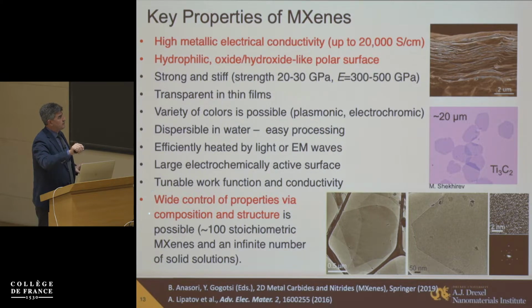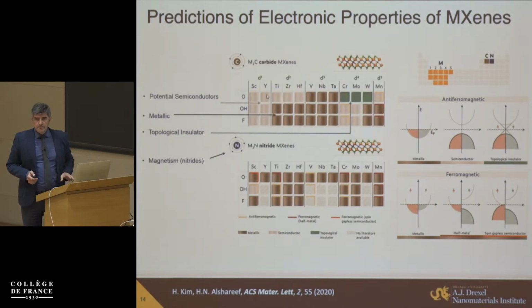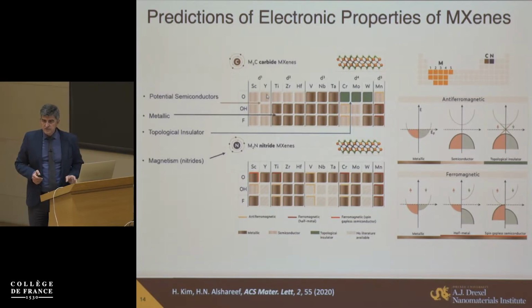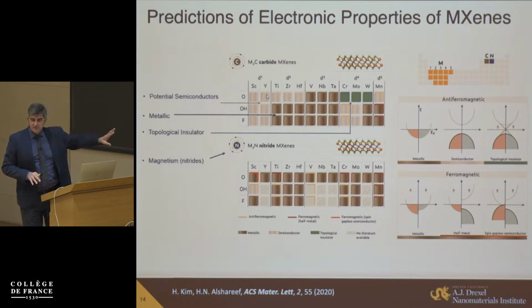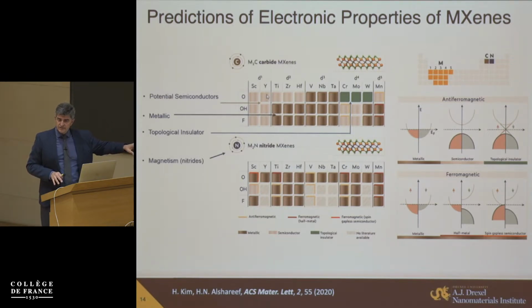The key message I would like to leave you with is that we have a material system where you can tune pretty much all properties as you need, from electronic to the chemical composition of the surface. Imagine you have pretty much a dozen transition metal oxides on the surface, and it can be hydroxide, chlorides, or other things. There are, by now, definitely more than 1,000 papers on DFT prediction of properties of various MXenes. There are some interesting things not necessarily related to energy storage, for example magnetism: ferromagnetic, two-dimensional ferromagnetic, antiferromagnetic materials, topological insulators, semiconductors, and others. Some of these properties have not even been experimentally verified yet. For example, we can get antiferromagnetic materials, magnetic glass, but ferromagnetic 2D have not been demonstrated.